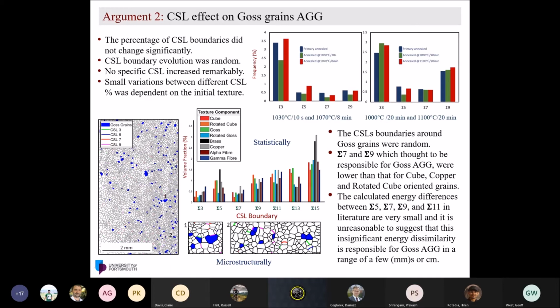Then we tried to understand how that happened statistically and microstructurally. So what we did, we took the sample which was annealed at 1,100 degrees Celsius for 20 minutes. We had like 10,000 grains to look at, and we specified each CSL grain boundary. For example, sigma 3 in green, sigma 5 in blue, sigma 7 in red, and so on, as you will see in the large map there. And then we took every single orientation within that map, including, for example, Goss in red, as you will see in the bar, in the volume fraction of the CSL boundary. So we tried to understand how much sigma 5, sigma 3, sigma 9 are surrounding the Goss grain and other orientations. And when you look at the data, we found out actually around these grains are very random, and